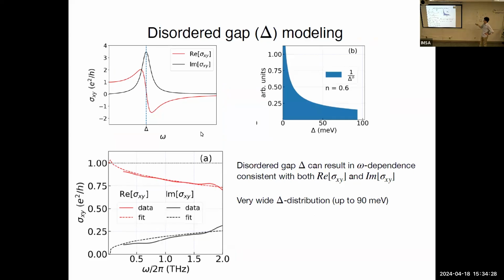To do that, again, we started with a very simple model, which you expect for a Hall conductance in a gapped system. And we were trying very different gap distributions, as in here, to see if we can match both real and imaginary parts of our data.